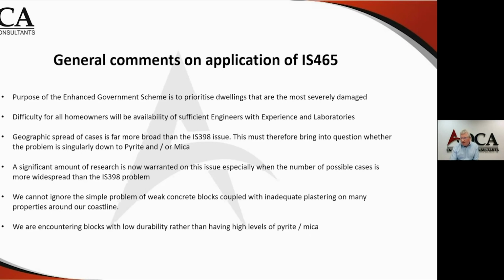I am not casting aspersions on the findings of what people are finding. But what I am saying is that the mere presence of pyrite, the mere presence of mica, does not mean that you have a problem or you are going to have a problem. And even if you've got some crazy paving cracking or web style cracking in your property, it does not automatically mean that low levels of pyrite is the cause of it. So as engineers, we must be forensic in our examination and understand that there are limits. If we only have extremely low levels of total sulfur as a result of pyrite or other materials that are within the cement because of the manufacturing process, it does not mean that that is the cause of the damage.